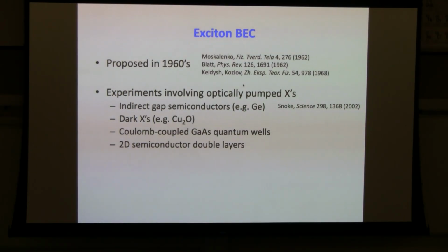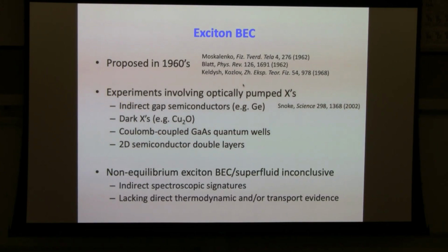And people also tried dark excitons in copper oxide, for instance. In these dark excitons, the dipole allowed transition is almost forbidden in this kind of material, so the excitons are also very long-lived. There are also other more recent efforts, such as looking at Coulomb-coupled gallium arsenide quantum wells, as well as 2D semiconductor double layers. In that case, it's really separating the electron and holes in real space, which reduces their wave function overlap, and you get very long-lived excitons as well. So you really want to have long-lived excitons, then you pump a lot of them, and you may be able to get into an exciton BEC. But so far, I can probably safely say that in this kind of non-equilibrium situation, relying on optical pumping, the signatures of exciton BEC have been quite indirect and controversial. And I think it's definitely lacking some direct thermodynamic or transport evidence for exciton condensates in this type of system.